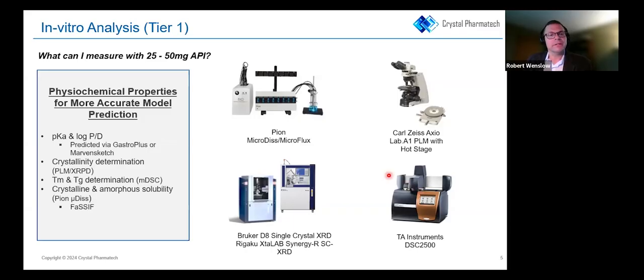And the one big piece of data we want to get is FaSSIF solubility, and a highly accurate FaSSIF solubility. This is with a crystalline and an amorphous material. But it doesn't have to be the best crystal. So I'm not saying I'm going to do a polymorph screening with 25 milligrams of material. What I'm saying is we can do a polymorph prediction with no material. And with the 25 milligrams, 80% of the time, we're going to get some type of crystal.